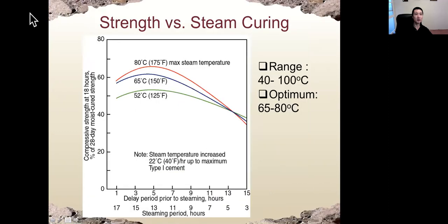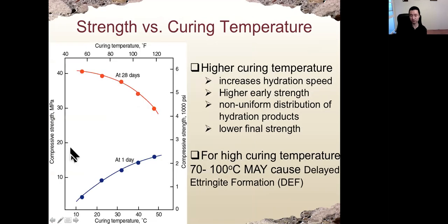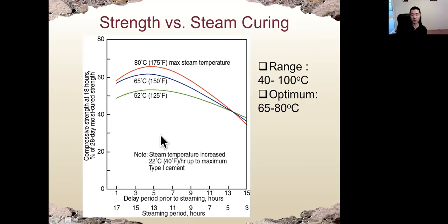Here's an example showing how the steam curing period and the delay period before steam curing affect the strength of concrete. The range of steam curing is around 40 to 100 degrees Celsius, with the best temperature around 65 to 80 degrees. By changing the parameters — the delay period and the steam period — we may change the final strength of the concrete. Again, this is just an example of how these parameters affect the performance of the concrete.